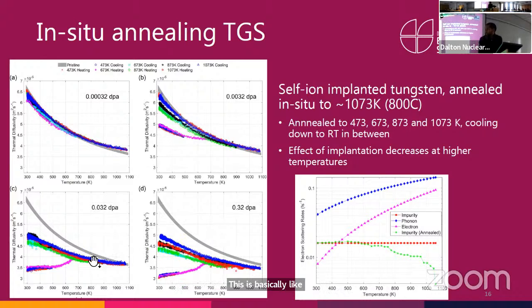And we saw this effect even in the other higher dose samples. In the lower dose samples, obviously, they started off at high thermal diffusivity, and we recovered the entire thermal diffusivity. It was like a pristine sample at the end of annealing. But for the high dose samples, no matter how many times we heated them up to 1073 Kelvin, we did not get a better thermal diffusivity than 5e-5, which led us to think maybe it's a different type of defect that we are healing.